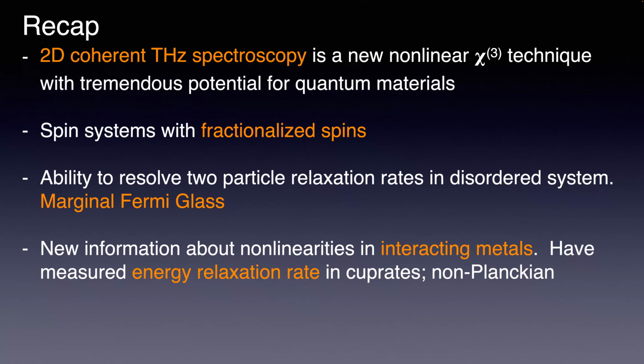We have these two laser pulses, and we delay one of the laser pulses sequentially with respect to the first one, and it's essentially a stroboscopic detection, so we can measure the electric field as a function of time. And that's an advantage because the detector is sitting there at room temperature and it's being completely bombarded by this thermal bath of photons, but they're all hitting with random phase, so they don't give any net current. On the background of that, you have this small extra coherent signal because you have this kind of boom, boom, boom that's always being picked out with a particular electric field at a particular time. And so that's how it works around it.